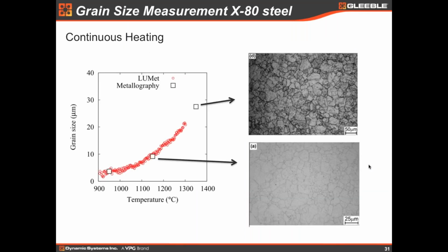I just want to show another example. This was originally made to study reheating of steel slabs. Okay, we have here these 3 points, which are microstructure generated by metallographic samples, and we have here 2 examples. This is the grain size and the temperature. So we see that in this first case, we have a very good correlation of the LUMet points that measure the grain size in real time and the metallographic sample.